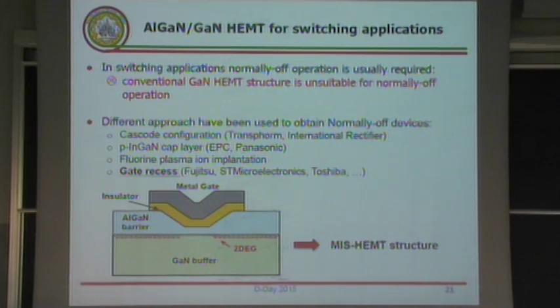And to obtain normally off configuration, many different approaches have been proposed by the different companies, as you can see here. However, in this work we have a device which obtained the normally off operation using the gate recess approach. So basically the thickness of the barrier beneath the gate has been reduced to reduce the polarization effect and deplete the two-dimensional electron gas. However, to limit the gate leakage, because the thickness of the barrier here is just a few nanometers, so we have a very high tunneling current, a very thin insulator layer was inserted to limit the gate leakage current.